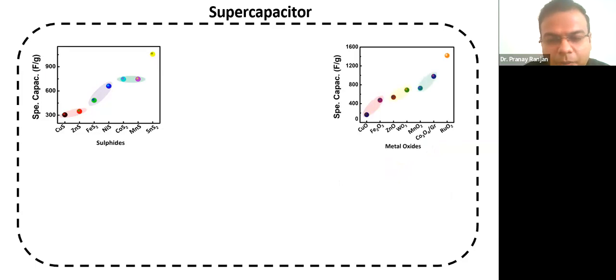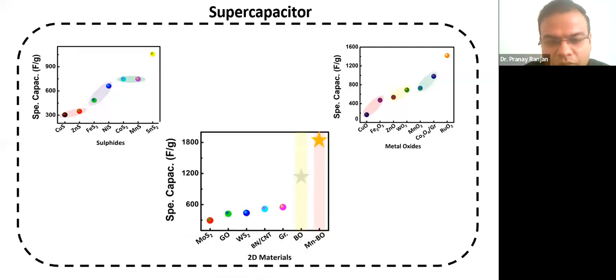While when you talk about metal oxide, we found that it goes a bit higher, like 1200 or 1400, but we have to remember that it's of ruthenium oxide, which is a very rare transition metal. Now in case of Borophene, we found that the result has been phenomenally, dramatically increased by 3-fold. We went up to 1800 farad per gram. So this was something new which we found in Borophene, and that can hugely impact real-time applications.